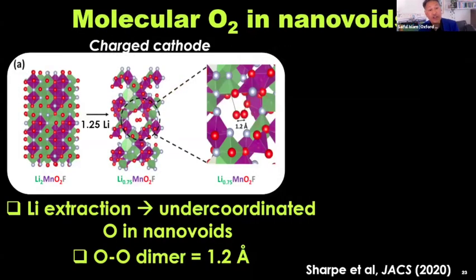So we did some simulations first, some unbiased simulation. We had no pre-bias in which way the simulations would go. On the left is the pristine oxyfluoride, disordered rock salt. Lithium is in green, manganese in purple, oxygen's in red, and the fluoride's in grey. As we extract lithium on charging, we produce a large number of lithium vacancies, but also under-coordinated oxygen. And what we find from our modelling is evidence of molecular O2 being formed in these nanovoids, in these cation vacancy clusters. And that oxygen-oxygen dimer has a bond length of 1.2 angstroms, which ties up with experiment for molecular O2.